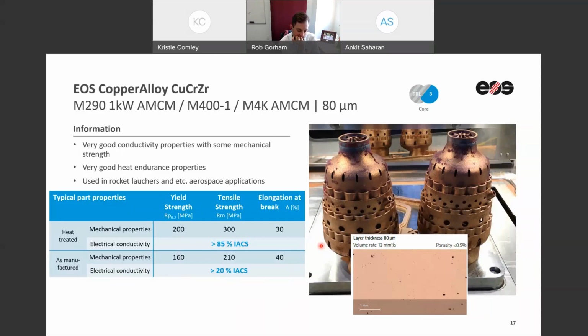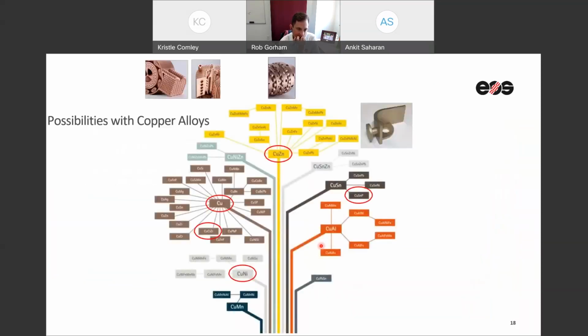And when you actually do it with 80 micron layer thicknesses, it's highly productive as well. So when we talk about possibilities with copper alloys, this is not the end. There's a huge range of copper alloy possibilities that you can actually see.